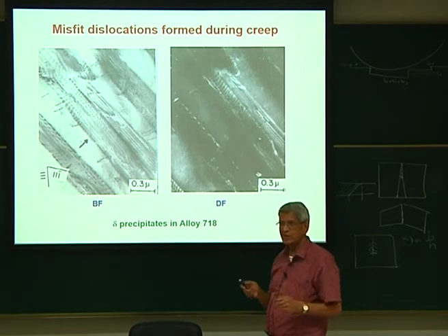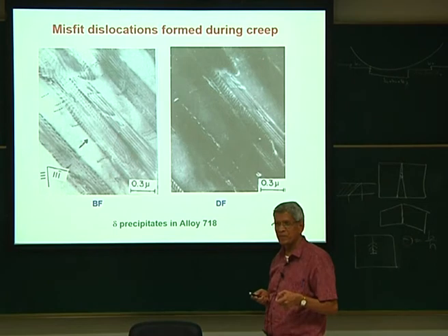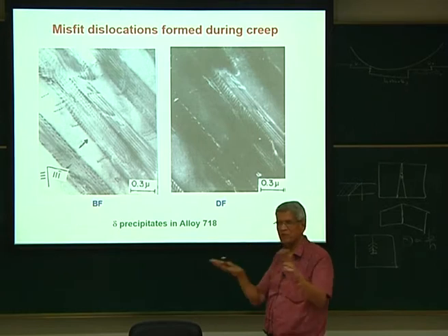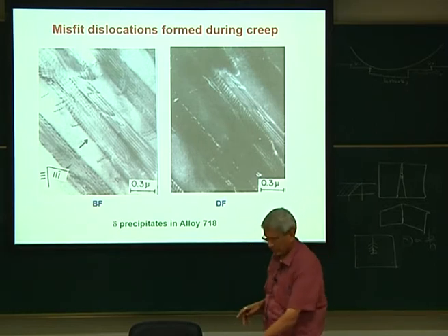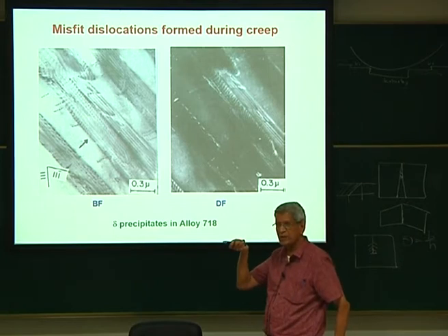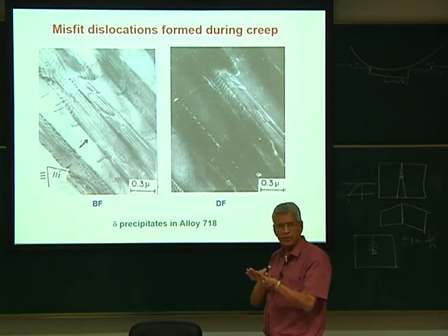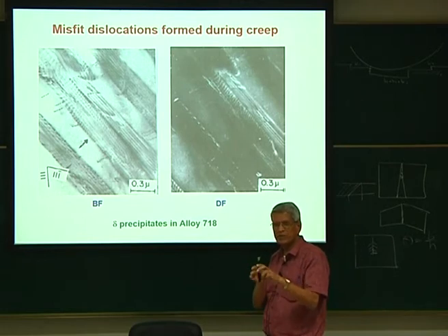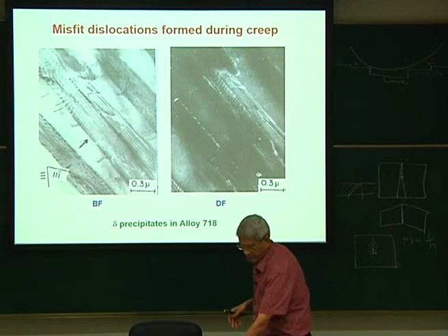these dislocations, if I try to heat this sample, will not move, because these are essentially misfit dislocations which are formed on the surface. They just remain attached to it. One way to check is to slightly increase the beam current. Locally it may get heated, and then you can see what happens. But in a sample which contains dislocations lying on a glide plane, when you just increase the beam current, you can see the dislocation starts moving in the sample.